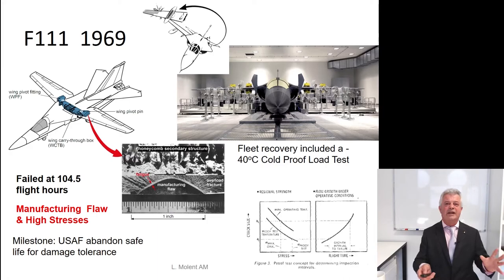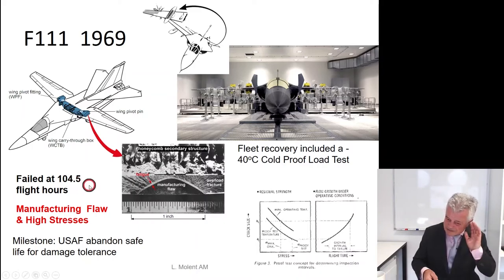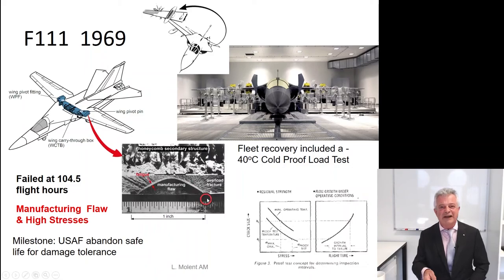F-111, moving on. The first F-111 flew in 1969. This particular beastie here failed at 104 hours out of a design life of 4,000 hours. Why, you ask? There was a manufacturing flaw. There's the manufacturing flaw. It's about 25 millimeters in the most highly loaded part of the airplane, and I showed you the final model of that earlier.